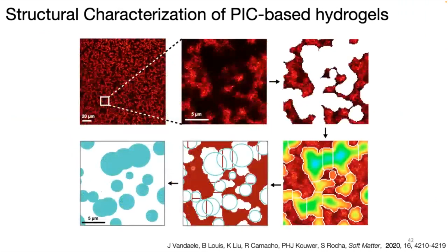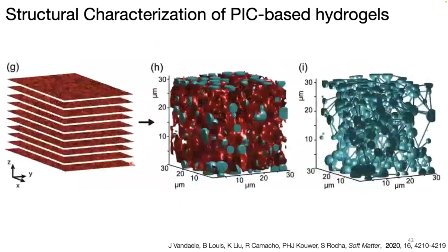And then what we do is some analysis on these pores. So we just segment it based on intensity, and then we can do this ball filling model, so that we try to fit the pores with some spheres to have an idea of how big these pores are. And because we acquire the data in 3D, you can actually calculate the pore size in 3D, and we can calculate the connectivity, so we can see how porous the material is, how connected the pores are.